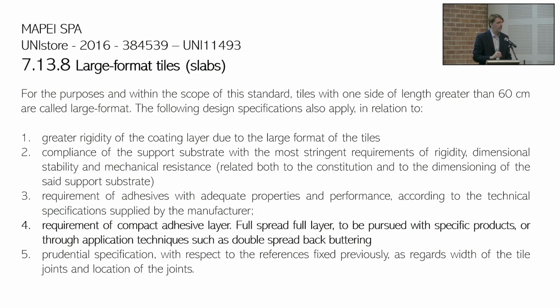It's not a law given by the government, it's not a mandatory norm, it's an advice contained in the Italian local standard that we did, not MAPEI, but the local Italian association with tile producers and adhesive producers, we did together as our best recommendation. Because if the tile is big, I don't want to have hollow, I want a different sound. I don't want to have hollows, voids under the tile, so I need to apply the double buttering system of the adhesive on the back and on the substrate.